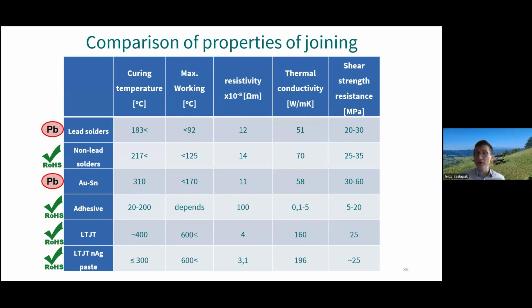So by comparing the developed technology with others, we were able to obtain lower resistivity, higher thermal conductivity, and comparable resistance to shear stresses. At the same time, the process temperature wouldn't exceed 300 degrees. We can even go a bit lower, although it may affect the parameters, with 5 megapascals pressure, which the electronic components survive easily.